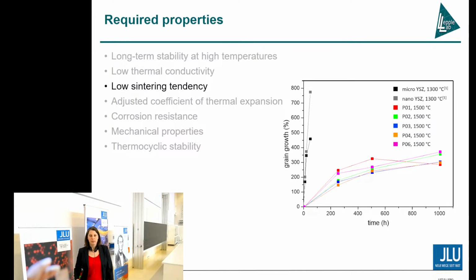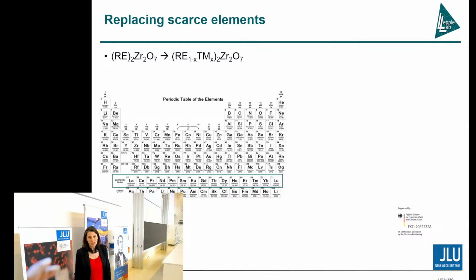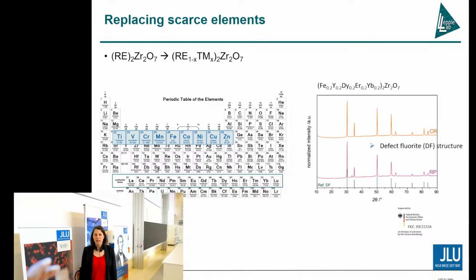So usually for thermal barrier coating materials, for example the zirconates which we investigate, we use a lot of rare earth elements which are quite scarce, and therefore we want to replace them. And we want to do it with the use of transition metal elements as shown here. And actually one of my PhD students is working on this, and she managed to introduce iron on the sublattice and got a phase pure material using two different synthesis techniques.